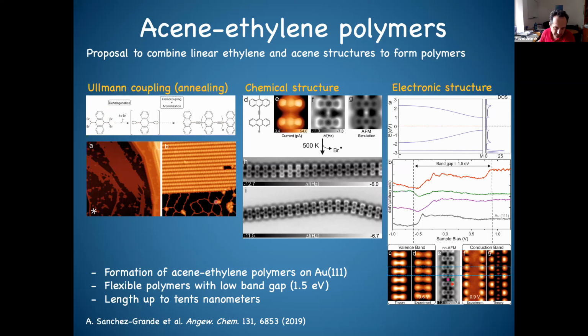Still, we have some residual bromines on the surface, but using this high resolution imaging, which was done by one of the chairmen of the Mini-colloquia, Bruno de la Torre, you can see at first glance that we form these anthracene polymers, which are ethylene bridged. And again, the double bond is very well seen in the image by this bright spot. Okay, so this is great. We also have very good agreement between the calculated band structure, conduction and valence band, which gives us the confidence that the DFT calculations are good enough for these systems.